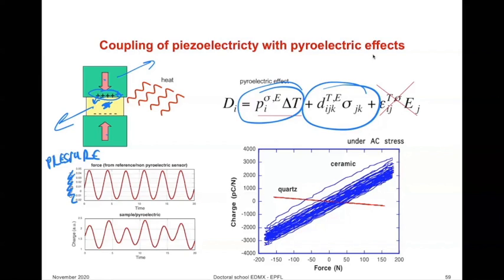It's not exactly sinusoidal. So what's going on here? Well, we have the temperature in the room is also changed while we are doing piezoelectric experiment. It's changed in an irregular fashion, and this charge that we get from the piezoelectric material is modulated by this term here.